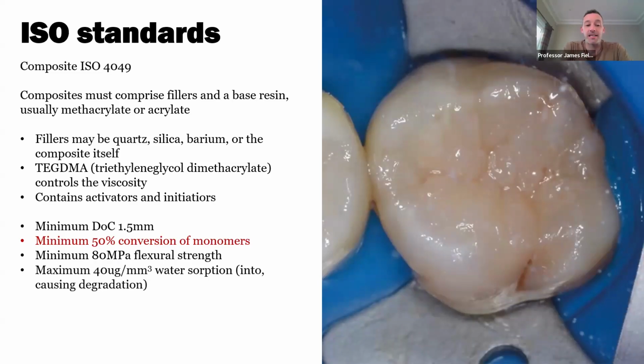And there's also a maximum amount of water that can be brought into the composite once it's in a moist environment. You might think that when you cure it, nothing happens and it's completely impervious to anything, but really any composite system will imbibe water into its structures around the edges and into its matrix. But it's stipulated that there has to be a limit. When it takes diluents into the structures, it starts to degrade composites, and this would happen to any kind of resin composite, but it would degrade over time.